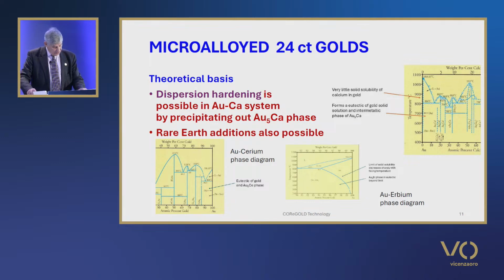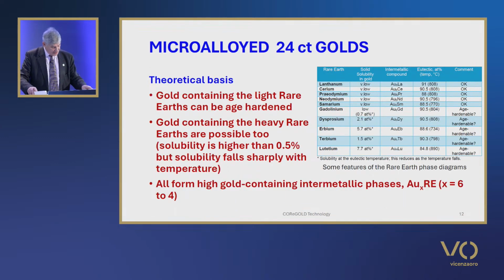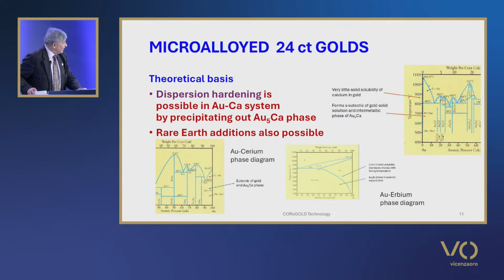Also, as the heavy rare earths have solubility at the eutectic temperature in excess of 0.5%, but a very low solubility as the temperature falls, it is possible that they may be amenable to age-hardening treatment with the precipitation of fine particles of the intermetallic compounds on annealing quenched material at low temperatures. And if we just go back again, in the middle there we can see the gold erbium phase diagram, or the gold-rich end of that, showing the limited solubility as the temperature falls, which suggests that it may be amenable.